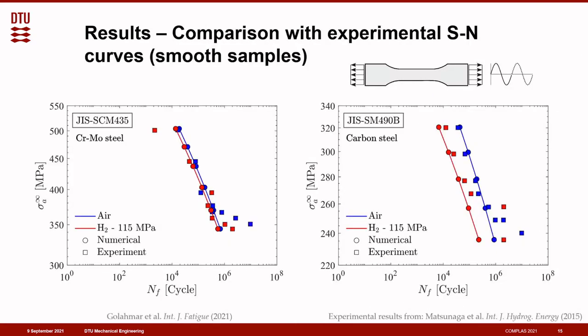And in conclusion, we compare our model predictions with S-N curves obtained from fatigue experiments on smooth samples. So basically, a typical dog bone specimen, which is widely used in fatigue experiments. The samples here are subject to uniaxial tension-compression cyclic loading and tested in both air and high pressure hydrogen gas. And this is done for two types of steel. So what we can see here is that despite the scatter, which is typically associated with these fatigue experiments, the virtual S-N curves predicted here are in good agreement with the measured data.